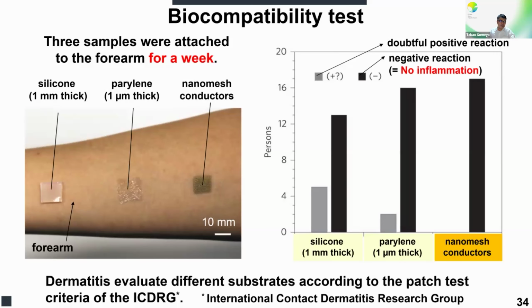So such gas permeability is very important to ensure the biocompatibility. So when the nanomesh conductors are put onto people's forearms continuously for a week, none of the patients exhibit any doubtful inflammatory issues. In sharp comparison, for a continuous film, such as 1 micron thick parylene or 1 millimeter thick silicone, both of them are known as biocompatible materials, yet the lack of breathability exhibits a fairly high risk of inflammatory issues.